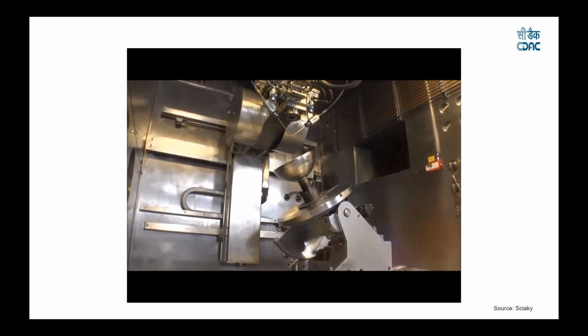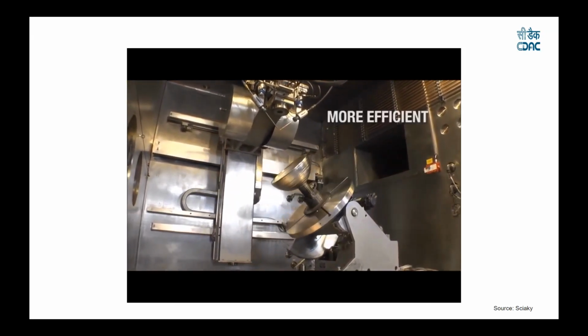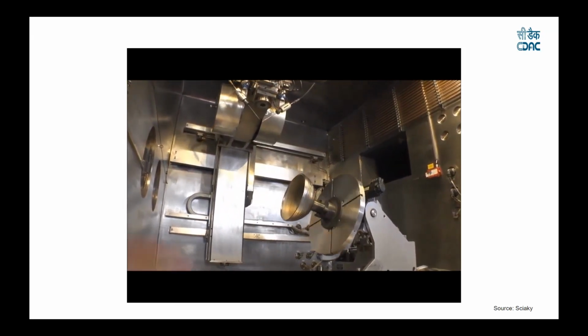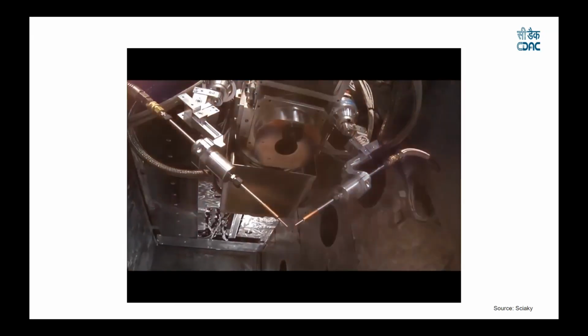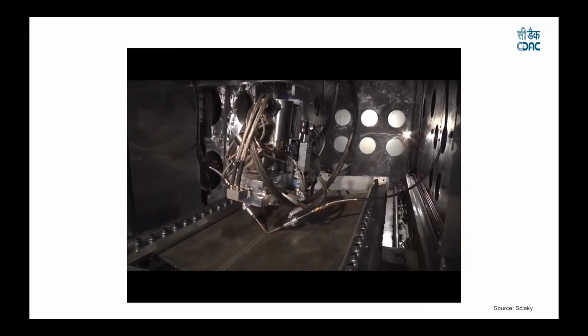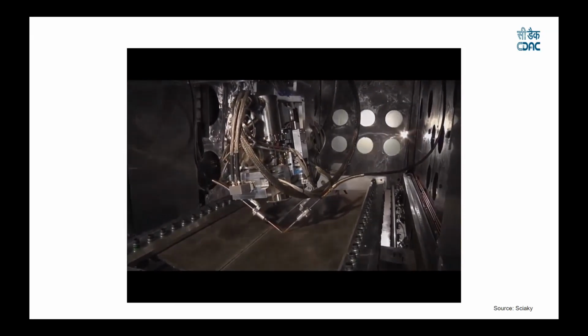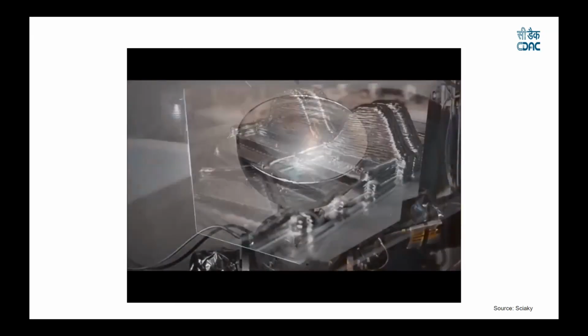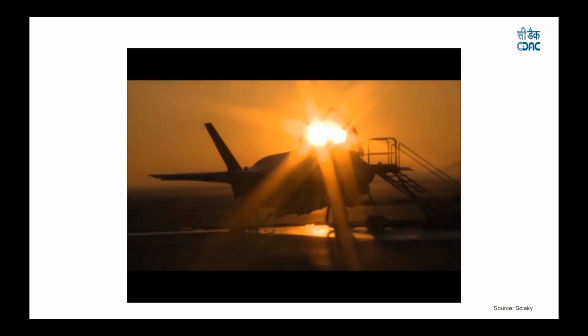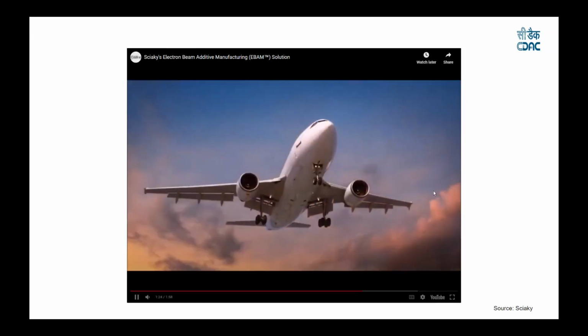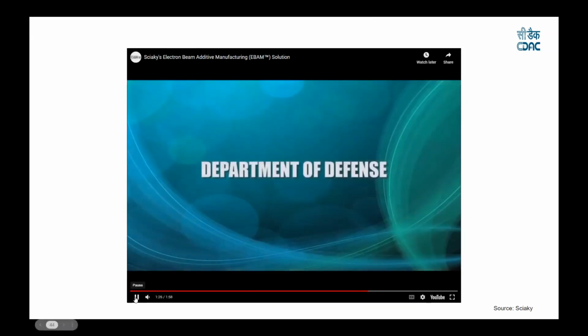Deposition rates can range from 7 to 20 pounds of metal per hour, which is significantly more efficient and cost effective than selective laser sintering processes that utilize messy powders. In addition, a dual wire feed system can be utilized with the EBAM process to increase deposition efficiency, as well as to easily switch to different deposition materials. So whether you need to produce a functional prototype or a run of production parts, the possibilities are virtually endless. Our technology partners include the Department of Defense.